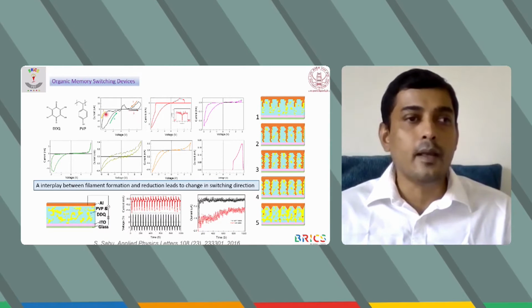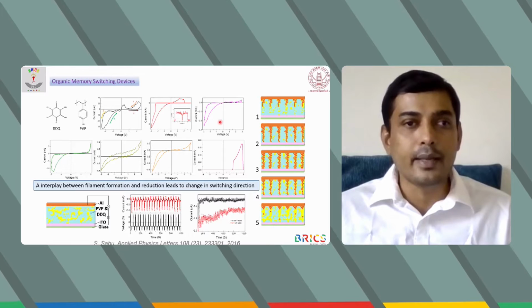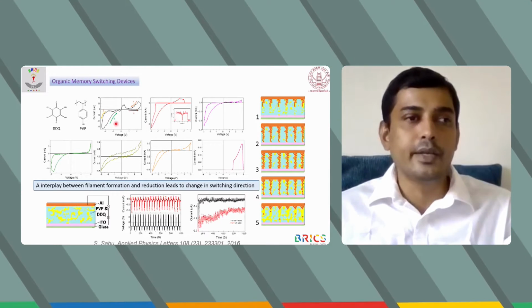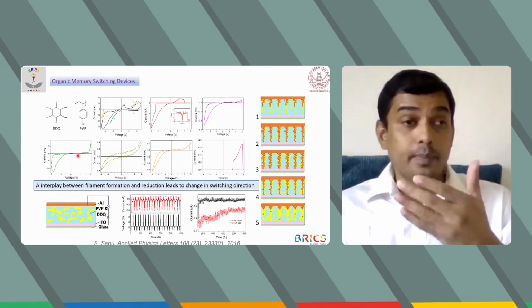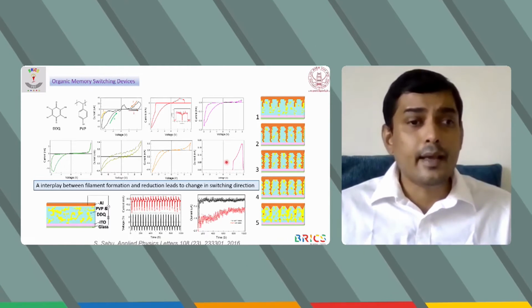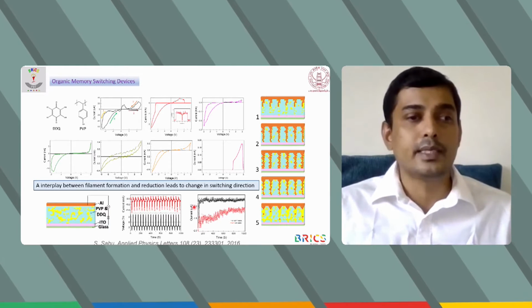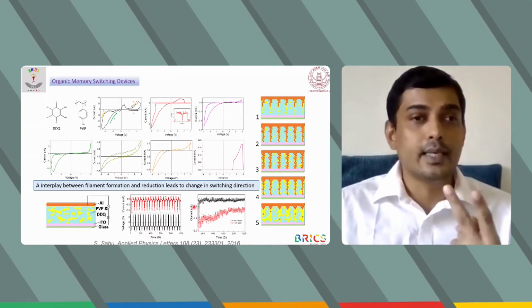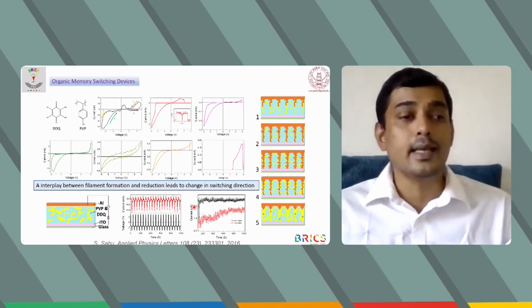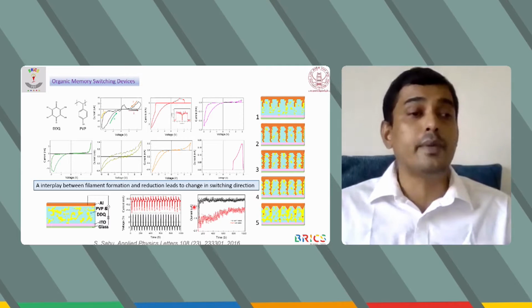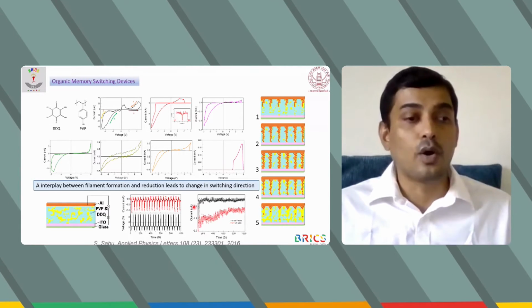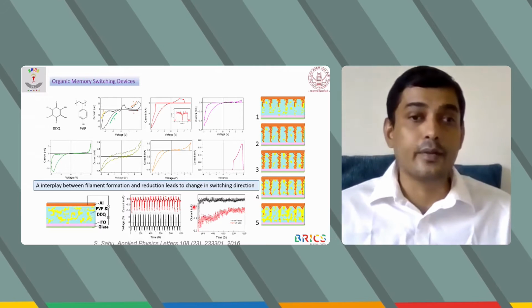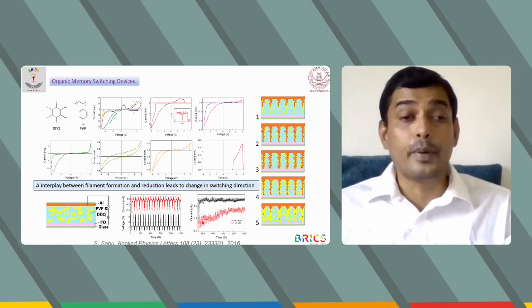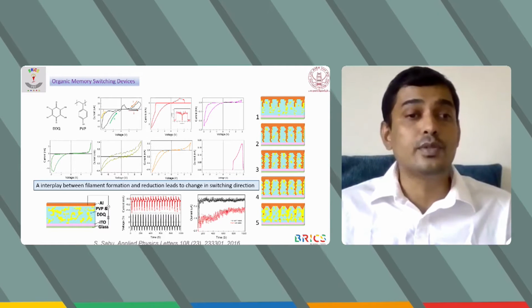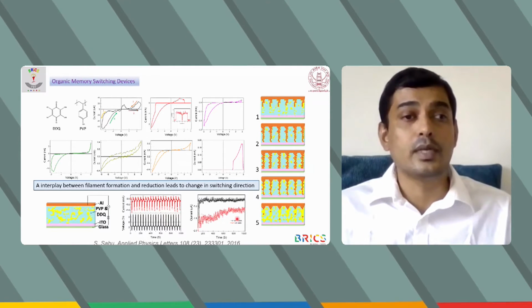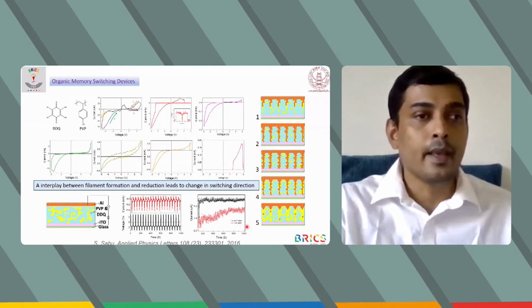Initially, it was showing the switching in the negative direction, but as you keep on going to increase the concentration of DDQ in the polymer matrix, the switching is shifting to the positive side. And here also we explain this behavior on the basis of two things. One, that is the molecule is reducing when we are applying bias. And the second is there is a filament, metal filament formation through the device, which is causing this kind of IV characteristic. And we also studied the other properties that can define whether the device can be used as a switching device or not. And we successfully studied this behavior from this device.